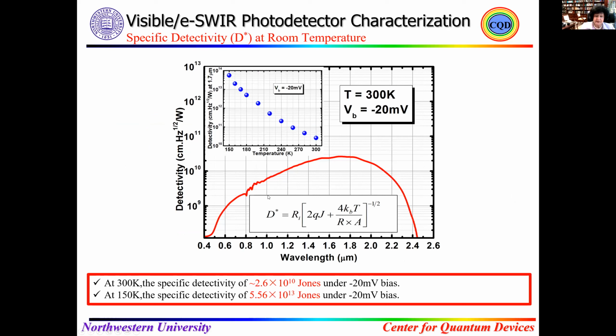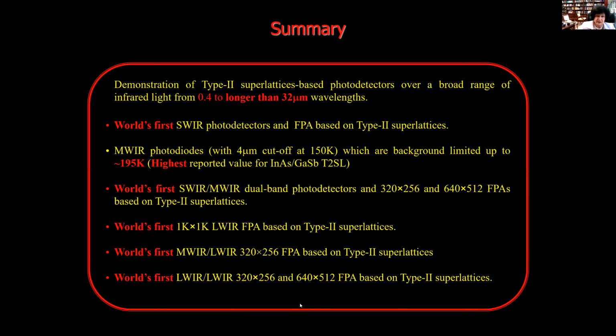And here is, again, just a recent result to show that, thanks to NASA and at the same time the DOD, we can see here the detectivity at room temperature with a bias voltage of 20 millivolt from 0.4 micron up to 2.4, again the cut-on and cut-off. At 300K, the detectivity is 2.6 times 10 to the 10 under minus 20 millivolt, and at 150 it is 5.6 times 10 to the 13. That is an excellent result. Not only is it a world first, but at the same time an excellent demonstration of the antimonide type-2 for that. So we did all of that.